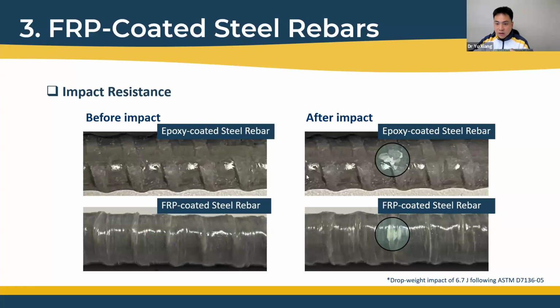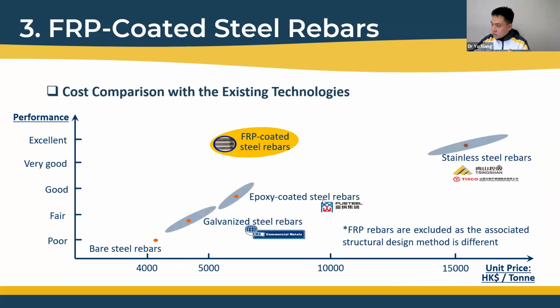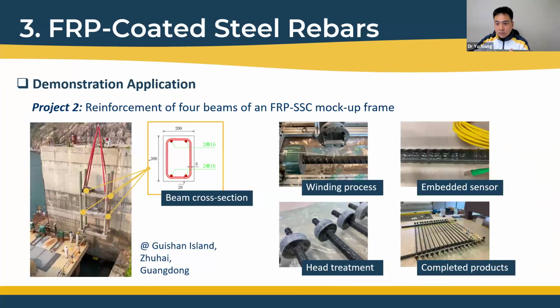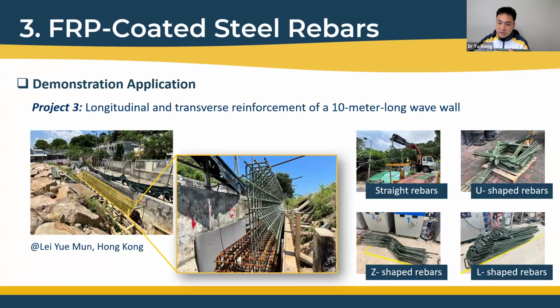The second part of this question is about project 3—were the shapes formed prior to FRP coating or by bending the rebar after coating? For Z shape and L shape, in this project we tried two methods: for these two, we bend them prior to making the FRP coating. For U shape, as requested by the contractor, we do the bending after making the coating with the FRP, in a hardened state.